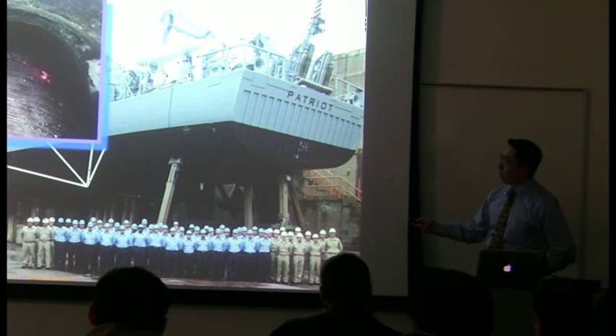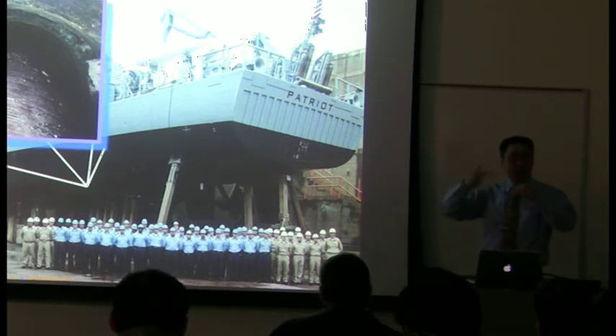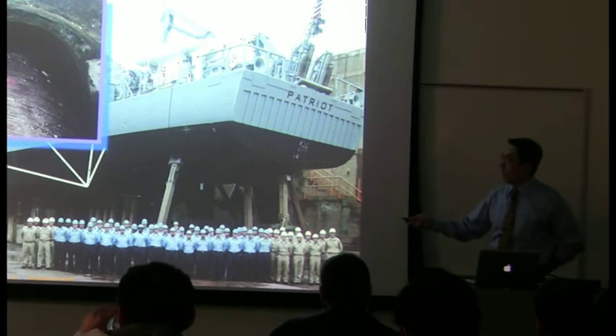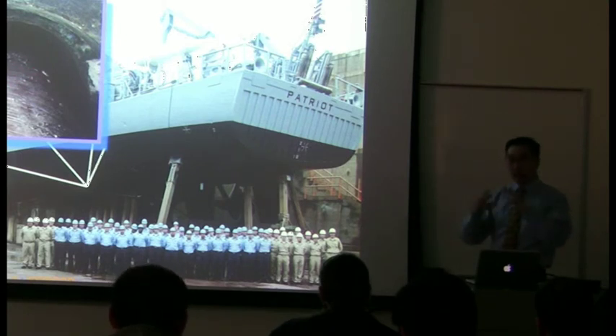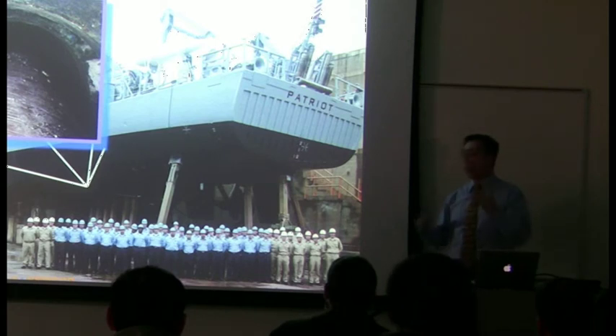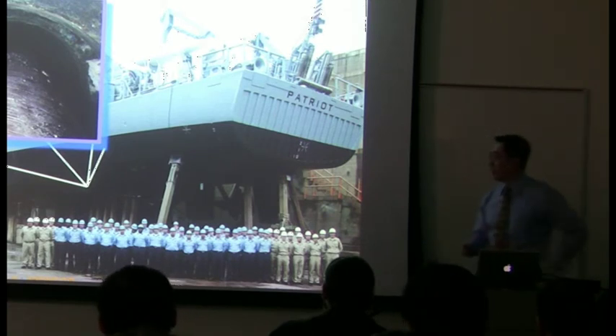And the main source for the wear is the biogrowth, calcareous buildup from exposure to seawater. The problem doesn't arise while the propeller is rotating. It arises during startup, because when you stop and try to start up, you have direct contact between the bearing surface and the shaft surface, and then abrasives form in between, so it starts scoring your shaft. In some cases, they've actually lost the propeller. It scored so much, it just fractured. But once it gets rotating, it's designed to form a water bearing, so you don't have contact with the rigid surface. So it's really startup that's the main issue.